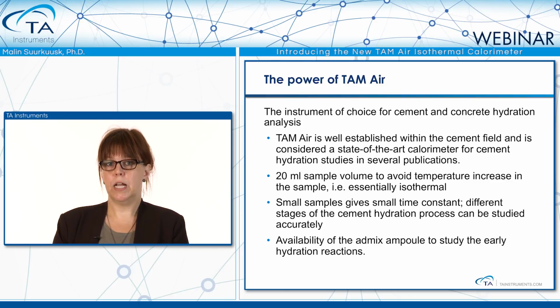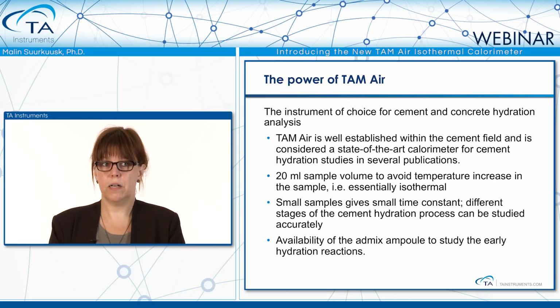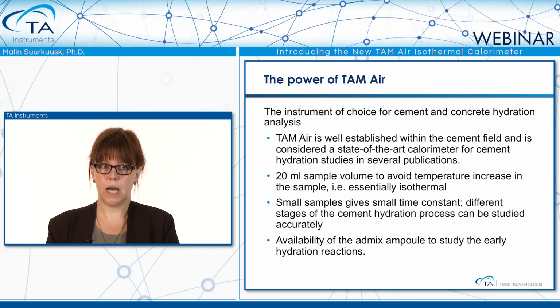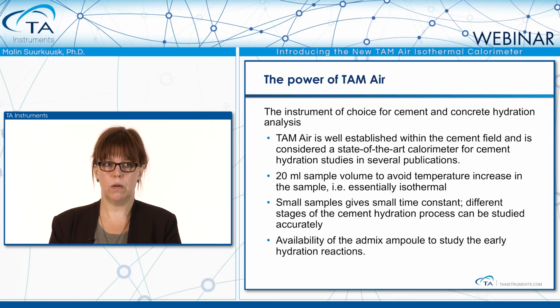And if we specifically look at using TAM Air in the cement and concrete analysis field, TAM Air is well established within this field, and is considered a state-of-the-art calorimeter in several publications for just cement hydration studies. It has a 20 milliliter sample volume to avoid temperature increase in the sample, which means that this is an essentially isothermal measurement. And the small samples also give a small time constant, so the different stages in the cement hydration process can be studied accurately.